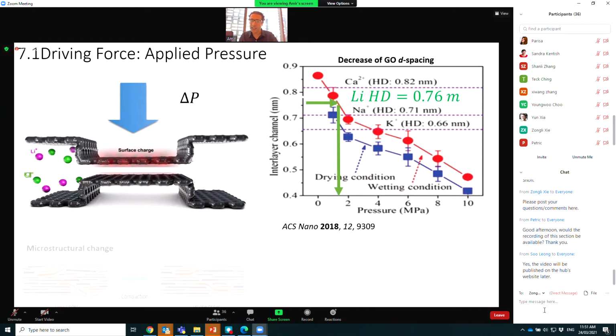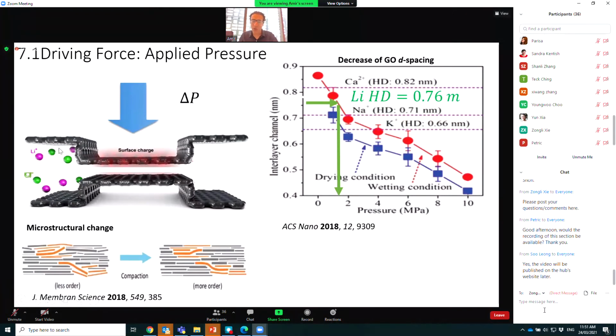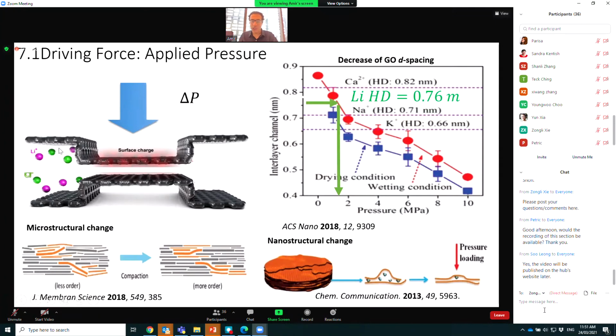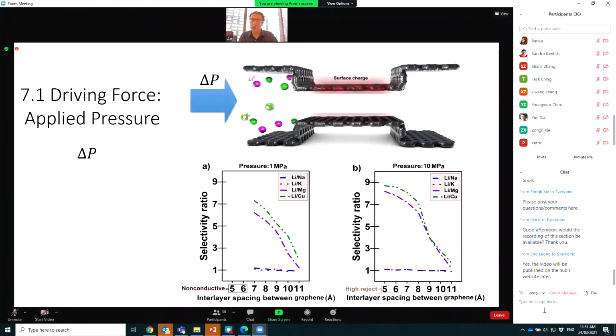In that case, you have a better selectivity. It can also improve the microstructure of your membrane and reduces the macro defects. However, when we provide pressure across the membrane, what we found is that at a pressure of 1 megapascal, our membrane didn't show any selectivity below 7 angstrom, whereas when we increase the pressure to 10 megapascals, our membrane shows selectivity.